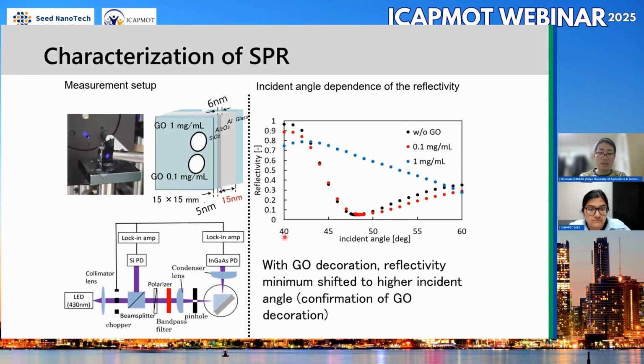And the right figure shows the incident angle dependence of the reflectivity for the sample without graphene oxide decoration, black curve, and the sensor chip with 0.1 milligram per milliliter graphene oxide, red circle. And the blue circle shows the reflectivity for the sensor chip with graphene oxide of 1 milligram per milliliter. So with graphene oxide decoration, the reflectivity minimum shifted to a higher incident angle. So we can confirm the graphene oxide decoration on the metal surface.